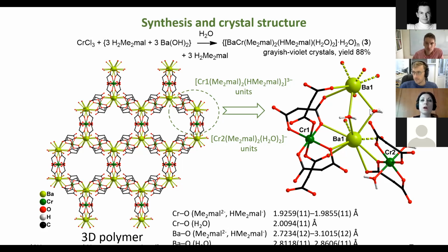This structure is formed by two types of mononuclear anionic units. The units of the first type are similar to those of compound 2. In the second type of anionic units, chromium is coordinated by two chelating dimethyl malonate dianions and by two water molecules. In the crystal, these units of the first and second type are linked together through coordination of oxygen atoms of malonate ligands to barium atoms to form a honeycomb framework structure.